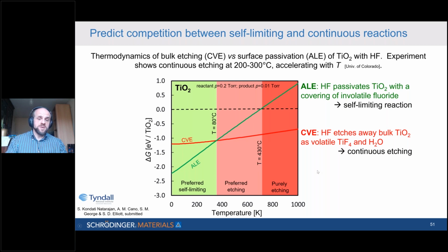And this is actually confirmed by experiment. So in Steve George's group, they tried to find that onset of etching, and they were unable to detect any etch products below 70 to 80 degrees C. Above 80 degrees C, they started to see a very faint signal for etching, and then beyond that, the continuous etching took over. So this is confirmed by experiment. So really nice to be able to predict the process window. As I was saying at the start, this is what we're trying to see, is what is the process window for deposition or etching, and modeling can help with that.